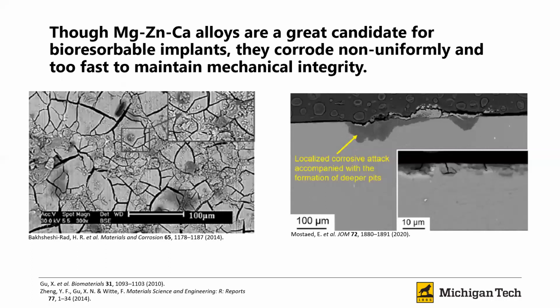So we have chosen magnesium, zinc, calcium alloys because they have a great biocompatibility and a strength similar to that of bone, but they corrode too fast in a bodily system to maintain the mechanical integrity that is needed for bioresorbable orthopedic implants.